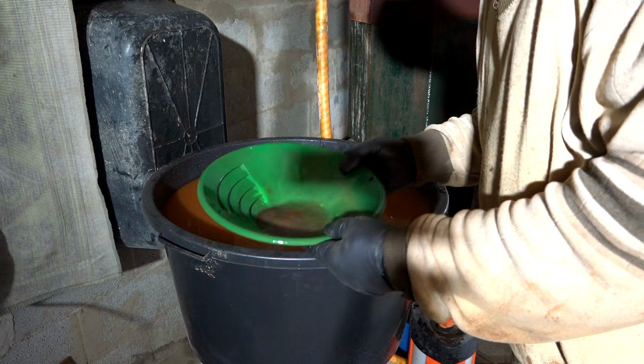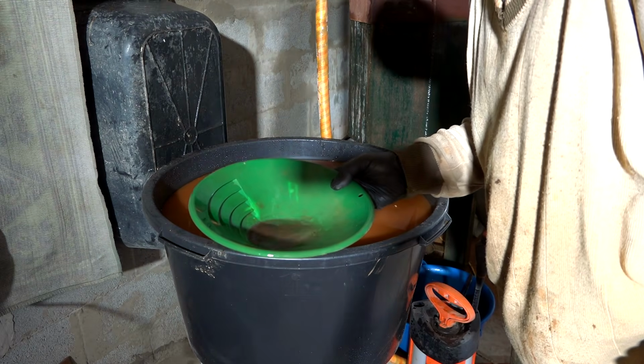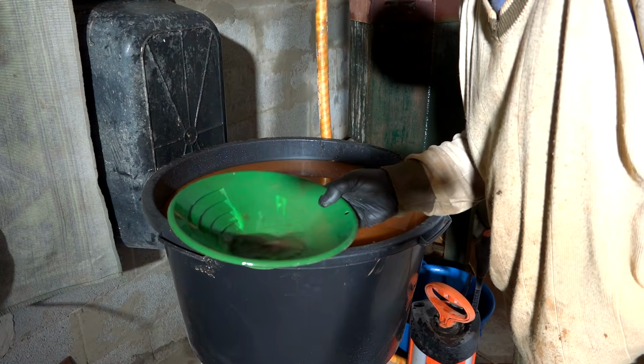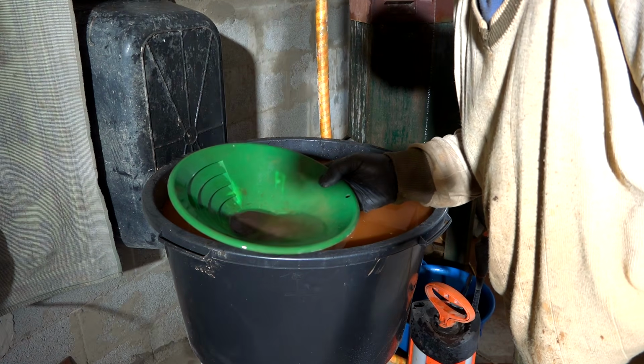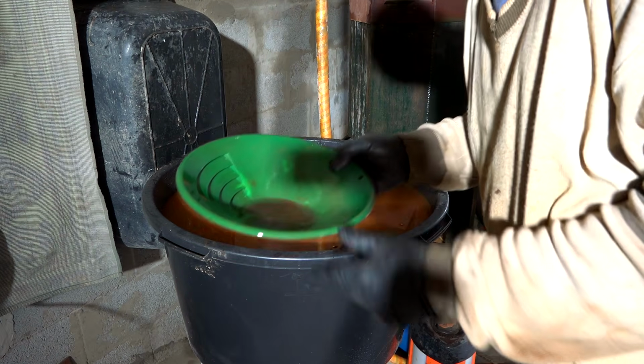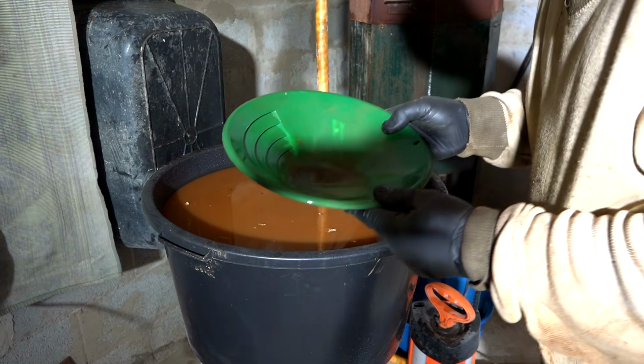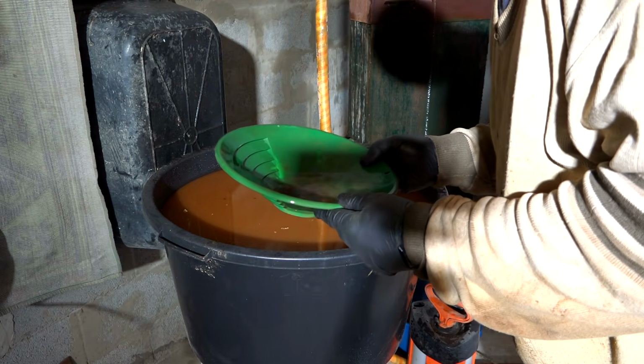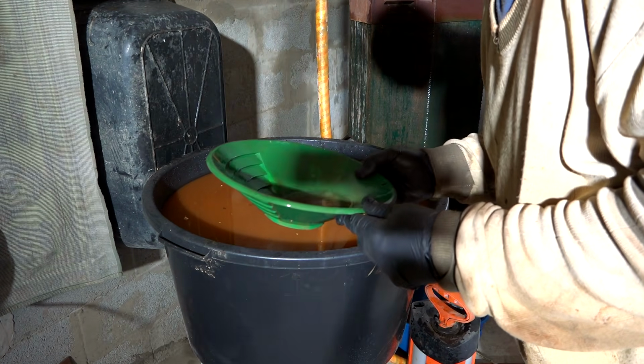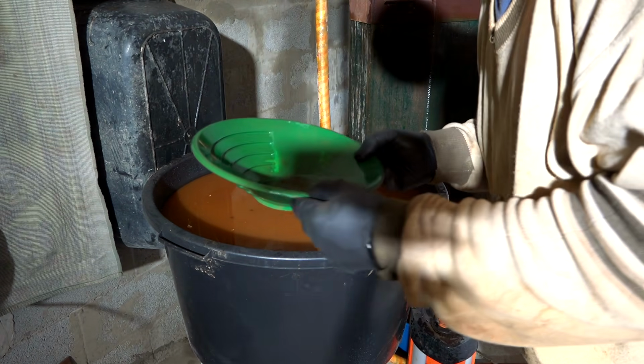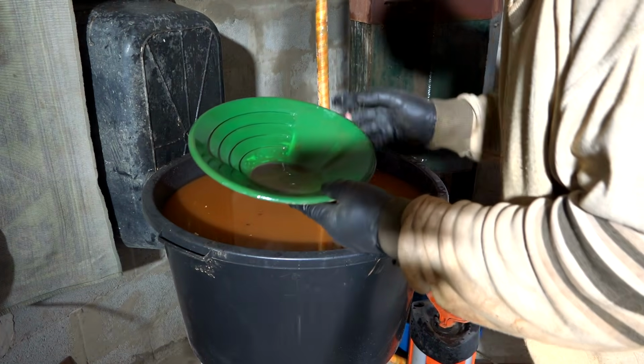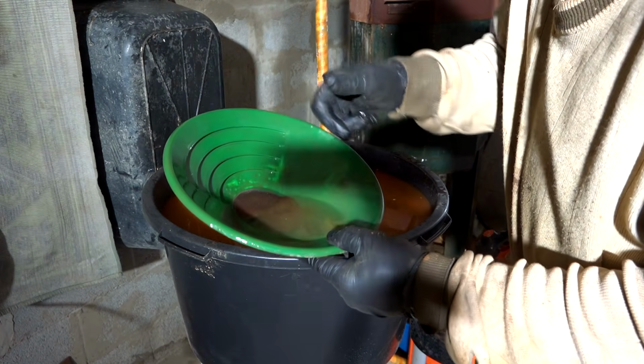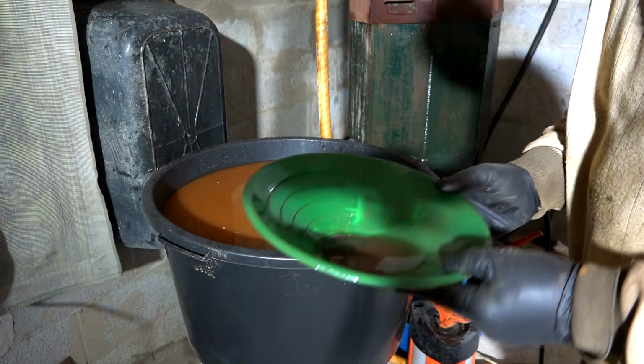Here, after washing, I get 3 kilograms of concentrate, which is still a lot of excess. My goal is to build a new device with smaller parameters and, after the second wash of the concentrate, obtain 100 grams of super concentrate. Think about it, 100 grams can easily be placed in a flask, dissolved with chemicals, or immediately melted with lead and used for cupellation.